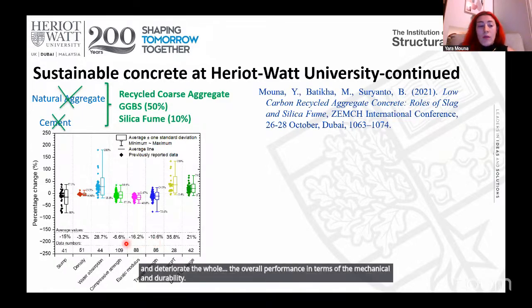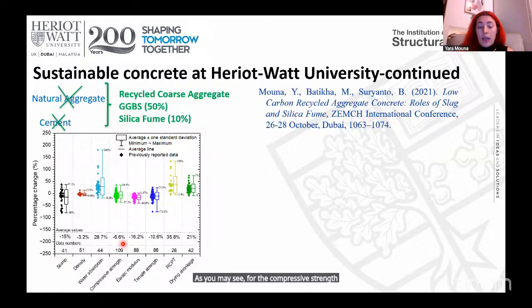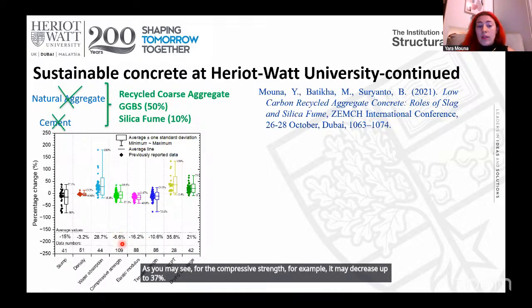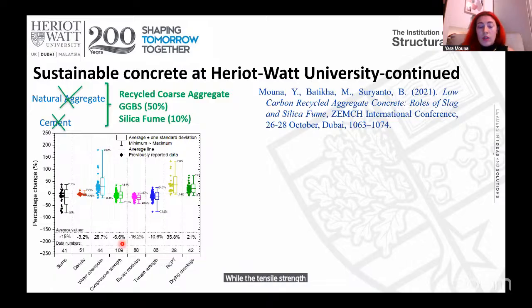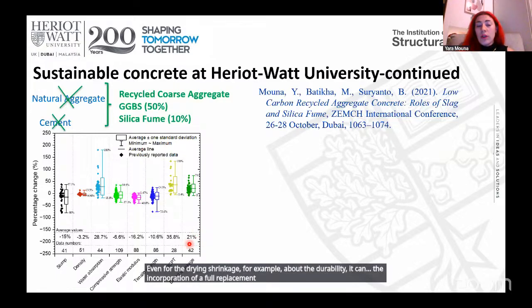As you may see, the compressive strength, for example, may decrease by up to 37%, while the tensile strength can decrease even more than this. Even for the drying shrinkage, regarding durability, the incorporation of a full replacement can increase the drying shrinkage by about 73%. So we can see that there's definitely a weak performance from the incorporation of the recycled coarse aggregate.